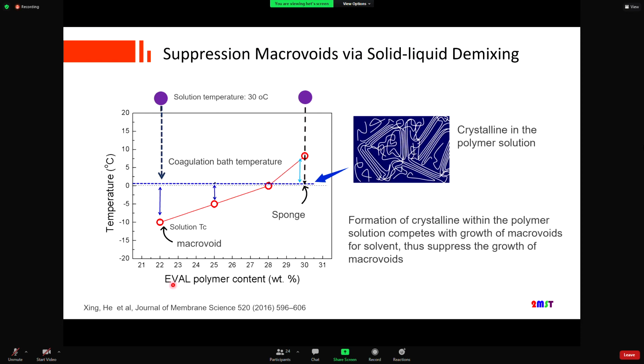If we plot the EVAL polymer concentration against the crystallization temperature of the polymer solution, you will get a phase diagram like this. The blue line is the coagulation temperature. By shifting this blue line up and down, we can control whether the polymer solution starts with liquid-liquid demixing or solid-liquid demixing. For example, at 22%, the Tc of the polymer solution is below the coagulation temperature, which means the polymer solution could initiate by liquid-liquid demixing instead of solid-liquid demixing.